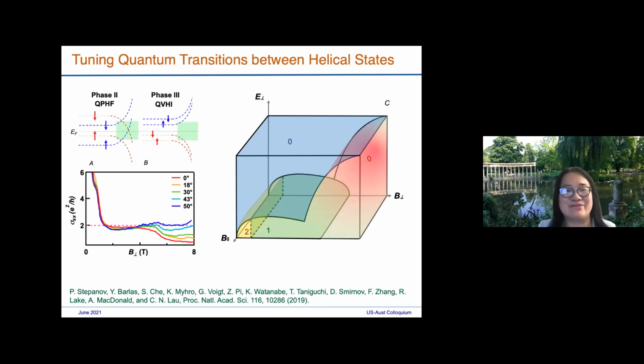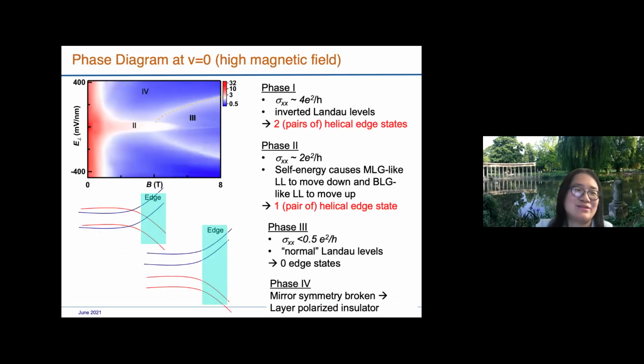Again, this is for the trilayer graphene. I think what's interesting is that this phase 2, which is one helical edge state, actually happens over a relatively small magnetic field. It happens above about one Tesla and persists to maybe 5 Tesla.